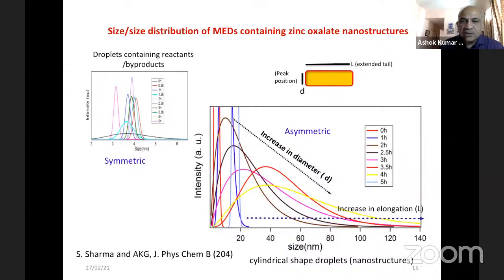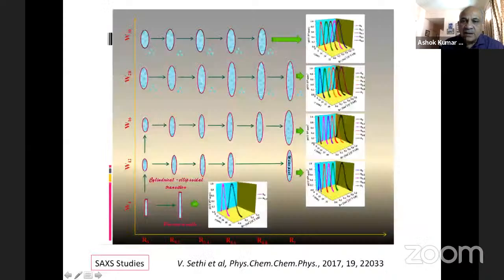Okay. Now we can also do small angle X-ray scattering. So just telling you another method where you can look at the scattering at very low angles, which is called the small angle X-ray scattering. And using that, you will get plots like that, and you can find out the length and breadth, and the asymmetry of the plot shows that you have a more elongated structure. You can do many other details. You can vary the W naught. The W naught is the ratio of the water to surfactant. And if you vary that, basically, you are varying how much water in the droplet goes.